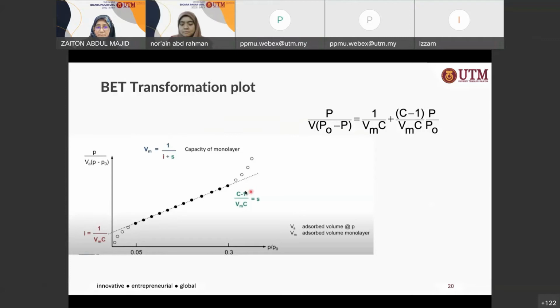Now, this is the BET transformation plot that we talk about, which uses the BET equation. So we plot Y versus X, which is your P over P naught. C minus 1 divided by VmC is your slope, S, and the intercept at the Y-axis, I, is equal to 1 over VmC. So Vm is equal to 1 over I plus S, the intercept plus the slope. From here, you can determine the monolayer volume, and from the slope you can also determine the C, once you get this.